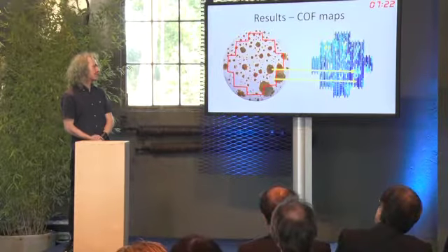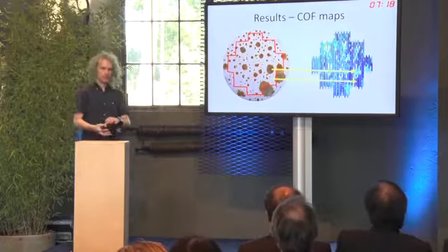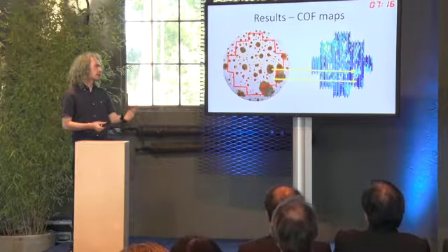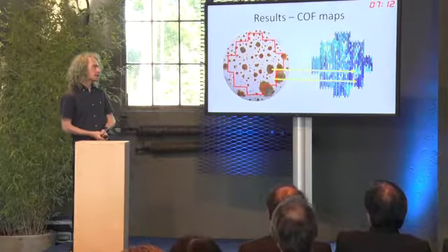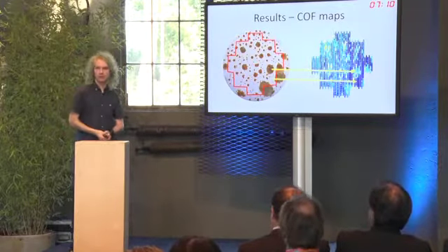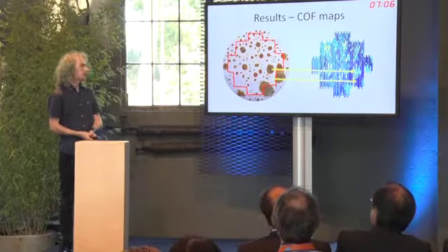So just pointing this out here, in the pitted areas, we get an increased roughness, which then causes the increased area, the increased coefficient of friction. However, outside of these areas, we do get a quite substantial decrease in the coefficient of friction due to the oxide being present there.